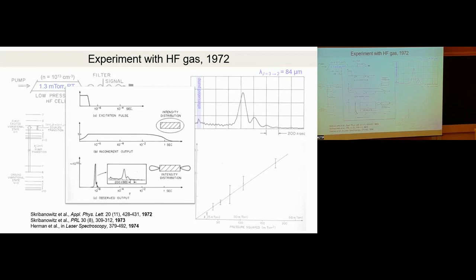They proposed this picture that later became quite influential and propagated to many reviews and books. You excite your sample with a fast excitation pulse. If it's a simple spontaneous emission, it decays on a certain time scale, and the intensity distribution around the sample is isotropic because each molecule emits light independently. In the case of superradiance, it's a directed emission, in the direction of the most emitters, because there should be some phase matching. And then it's a very short pulse of light.